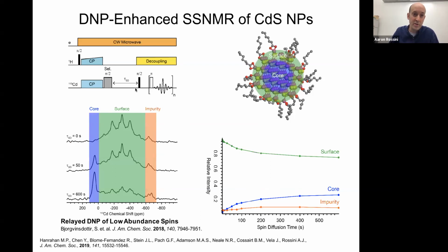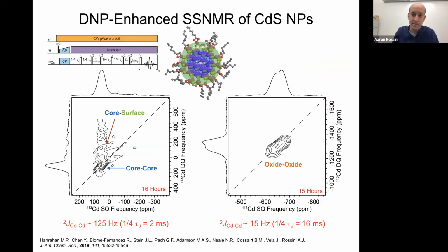Now we can do some other experiments. This is a cadmium-113 spin diffusion experiment. What we do here is we polarize those cadmium atoms on the surface, and then we watch how cadmium-113 spin diffusion can transport that polarization into the core signal. This experiment's nice because it really does confirm that we are seeing the signals from the surface species.